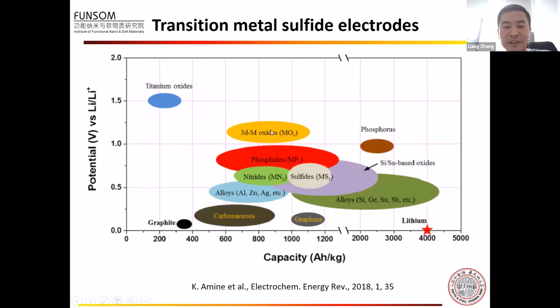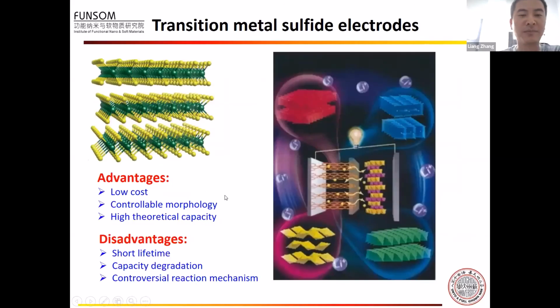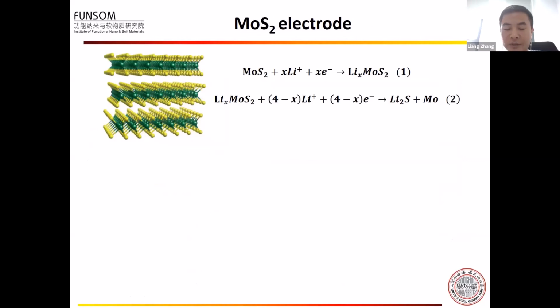Among the different materials, including the metal oxide, metal sulfide, and metal nitride, metal sulfide electrode attracts intensive attention, mainly because of the advantages of low cost, controllable morphology, and high theoretical capacity. However, metal sulfides also have some disadvantages, including short lifetime and very fast capacity degradation, and especially the reaction mechanism is still controversial. Therefore, we first investigate a very common electrode, moly-sulfide.